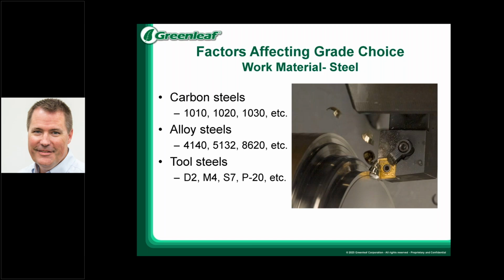These materials help designate what the alloying agents are in it, the material itself, and what the carbon content is. The lower the number, the last two digits are, the lower the carbon content, which also can help indicate what the difficulty of machining may be. Standard material with a low carbon content, such as like 1010 carbon steel, low carbon content, very difficult to chip. It's much more ductile. So having considerations for that when selecting your chip form and grade are important.